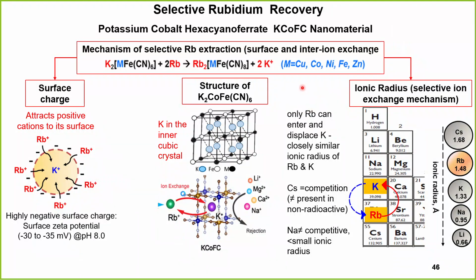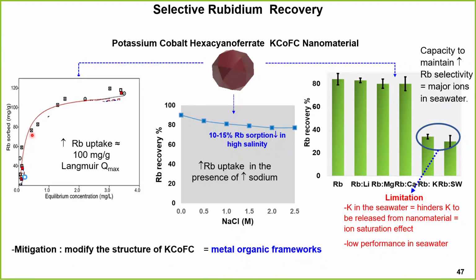And this is the structural image, and we also have the ionic radius of the material. If you look at rubidium and lithium, they are our target compounds. The radius size of rubidium is 1.48, and lithium is 0.66. So we looked at how these compounds can be collected from this structural ion chain, and then we measured the basic absorption experiment. You can see the rubidium absorbed capacity is almost 100 milligram per gram, which is a good capacity for this absorbent.